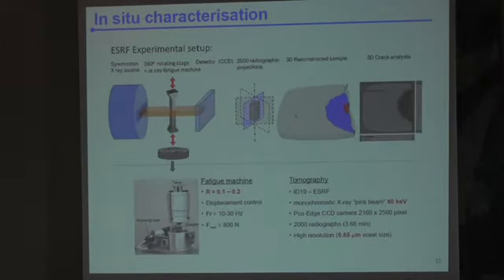We did synchrotron tomography, because lab tomography for fatigue cracks, in spite of the low voxel size, is really still a challenge at the moment in the lab. It's not only a matter of voxel size, it's also the way you're detecting the signal. And in synchrotron, on top of the attenuation contrast, you add the phase contrast, which is kind of a diffraction effect, and that helps you a lot in detecting the crack tip.